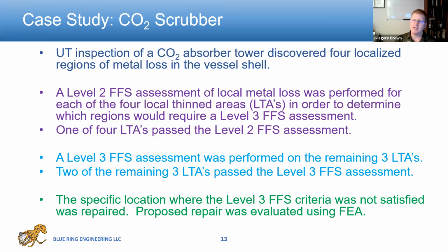So what we had in this case was what's called a CO2 absorber tower. It is a tall, narrow pressure vessel, and it had regions of metal loss in the shell. There were 4 regions of metal loss. An inspection was done to determine how much wall thickness was there. As it turns out, this metal loss was below the designed minimum thickness.